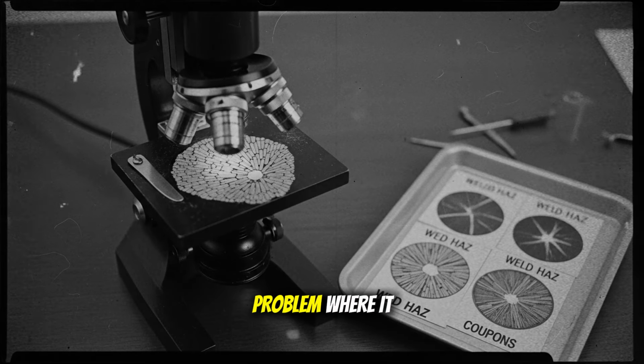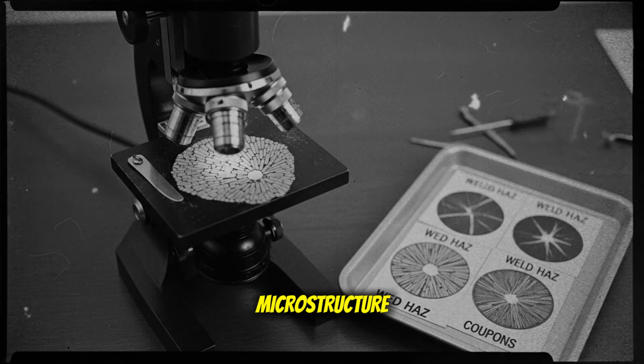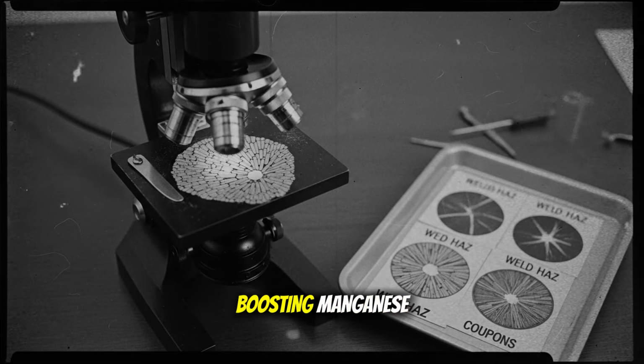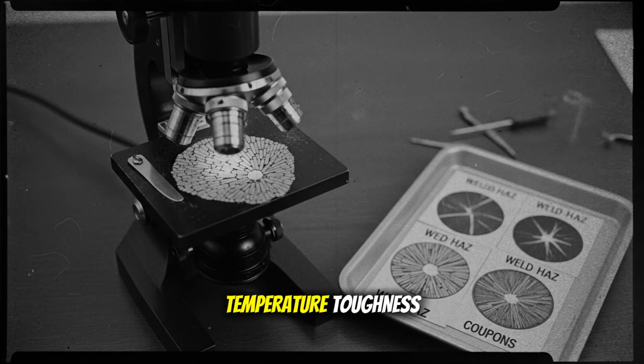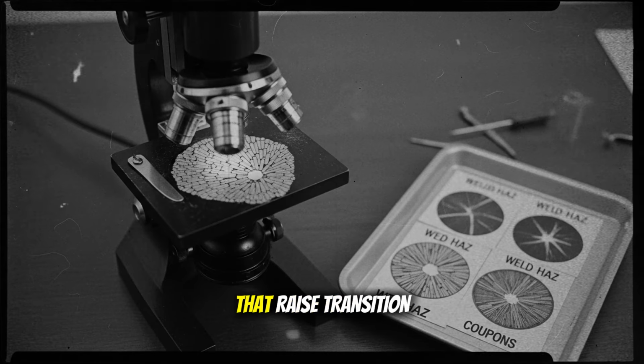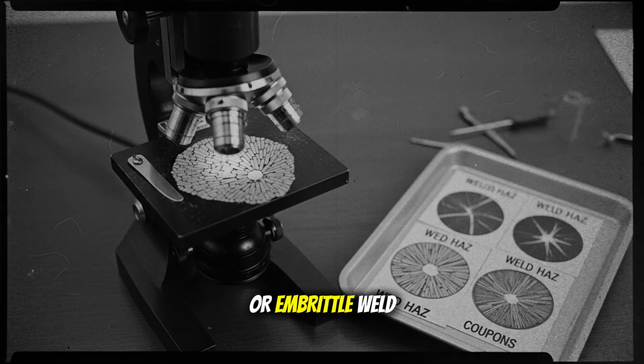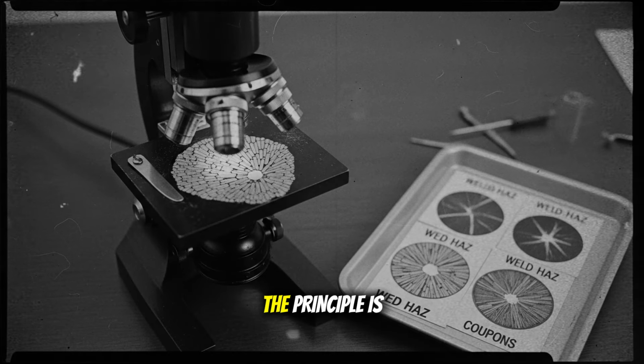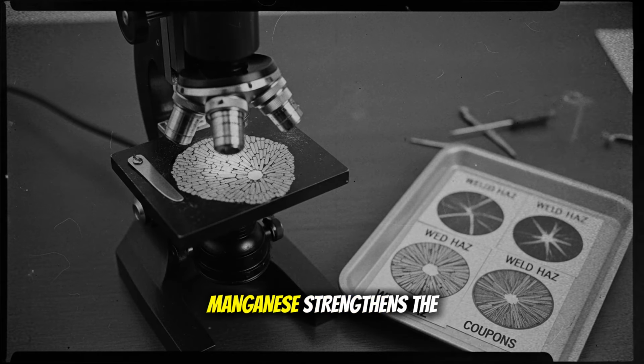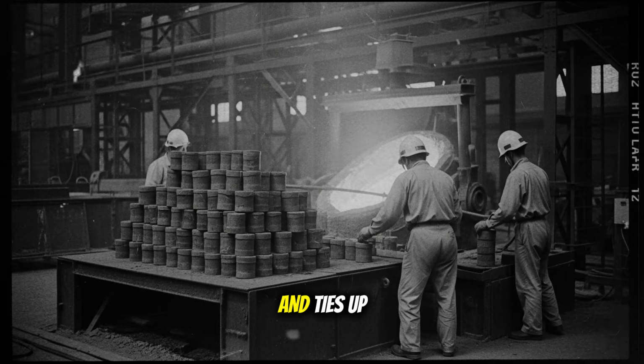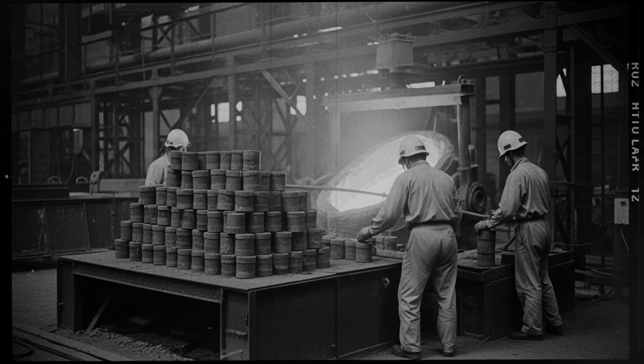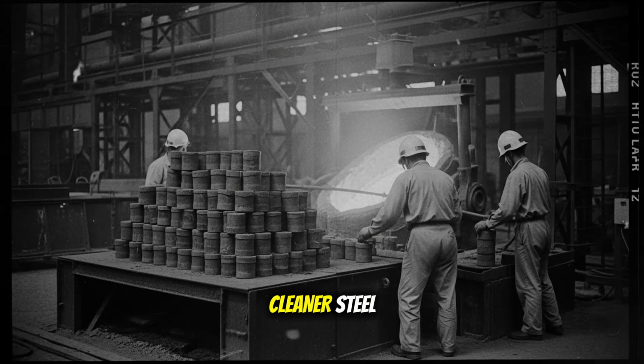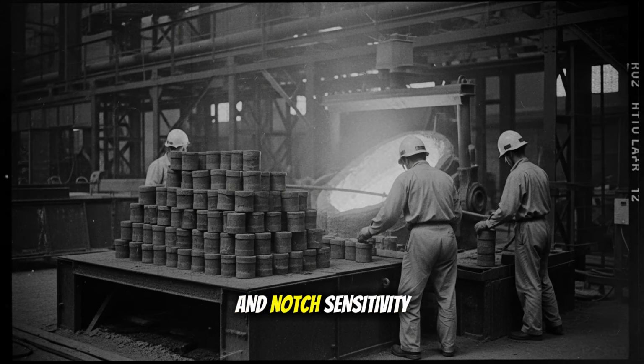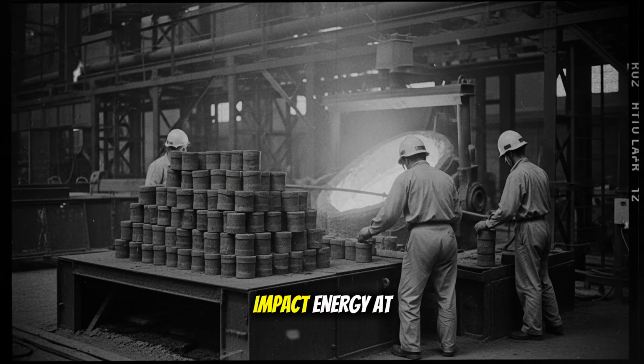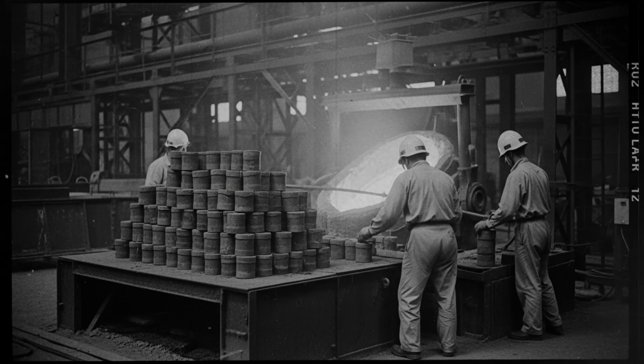Metallurgists attacked the problem where it lived, in chemistry and microstructure, lowering carbon and boosting manganese to improve low-temperature toughness while cutting impurity levels that raise transition temperatures or embrittle weld zones. The principle is well established. Manganese strengthens the ferrite matrix and ties up sulfur as MnS, while a lower carbon content and cleaner steel reduce brittle phases and notch sensitivity that conspire against impact energy at low temperature.